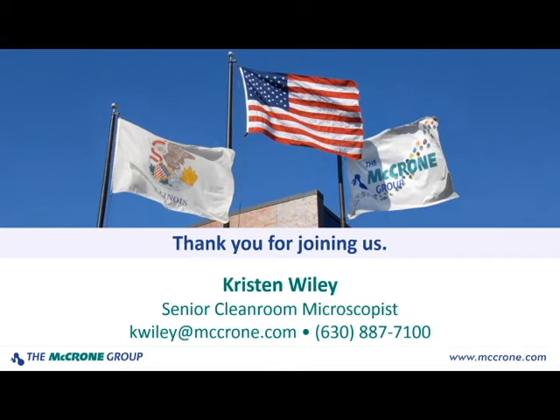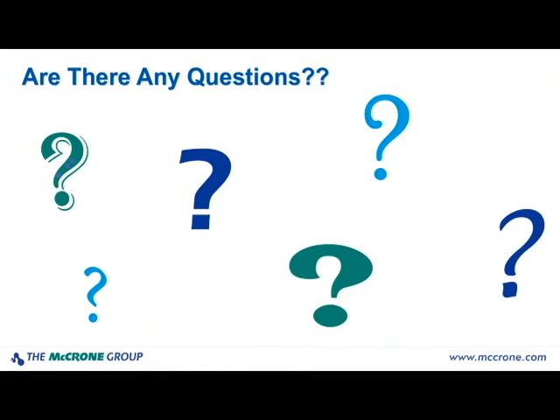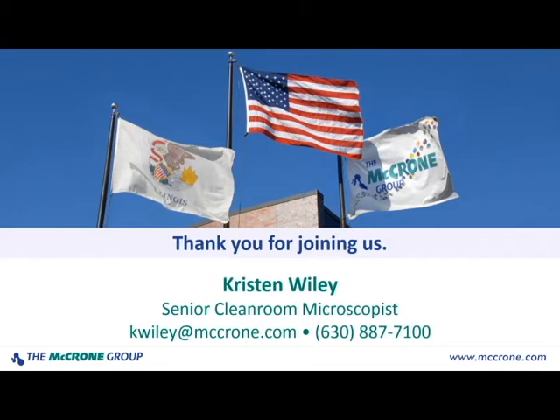Yes, let's see. I missed how you mounted the KBr to the special holder. Is that two-sided tape? The KBr holder itself is something that McCrone Microscopes and Accessories sells. It's a special holder that is hollow in the middle, and there's a very light adhesive around that hollow opening. So the edges of the KBr crystal are attached to that adhesive, but leaving the center of the KBr where your samples are propped hollow. So the laser can actually come up through the KBr crystal and hit your sample. If that answers your question.